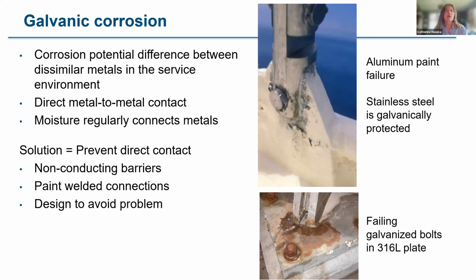I'm showing a picture of a cast aluminum that was painted, but the arm above it moved, so the paint wasn't going to last. And you can see there's galvanic corrosion of the aluminum under the stainless steel piece. The bottom picture was taken at a very wealthy person's private residence. These stainless steel structural sections held the house several floors off the ground because of storm surge concerns, but the bolts were galvanized steel, and they are corroding at a highly accelerated rate.